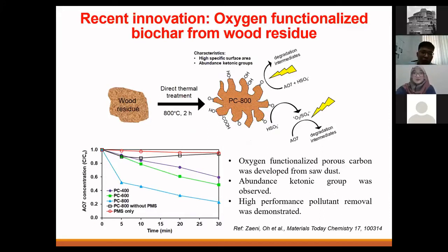She used this wood residue, and instead of functionalizing it with nitrogen, she functionalized it with oxygen, which means that she doesn't use any precursor. She just seals it off and heats it up to 800 degrees Celsius. And what we get is something that is also very effective in removing pollutants.